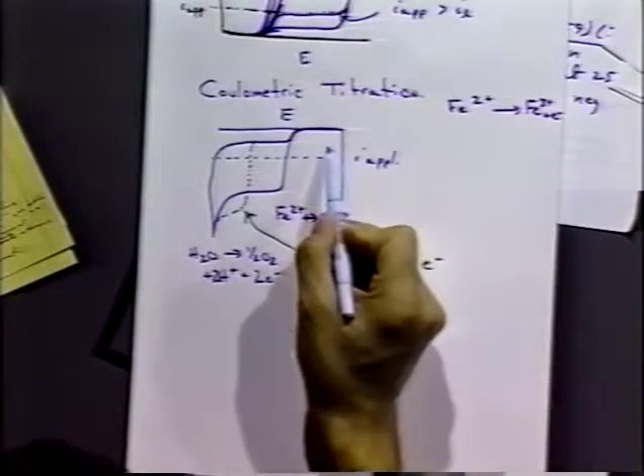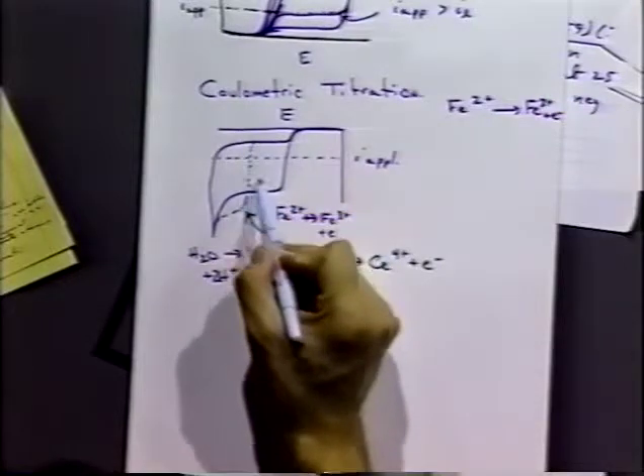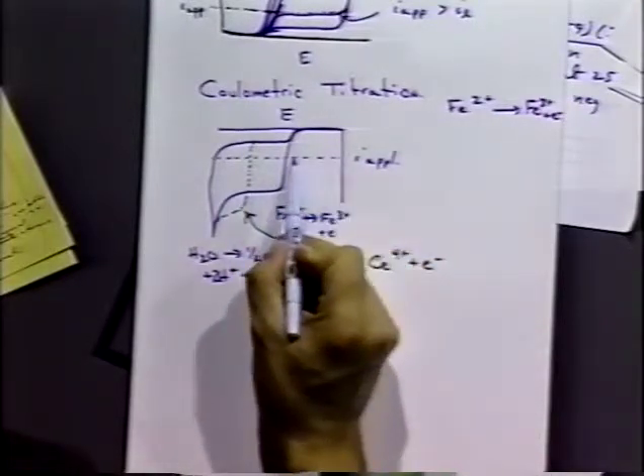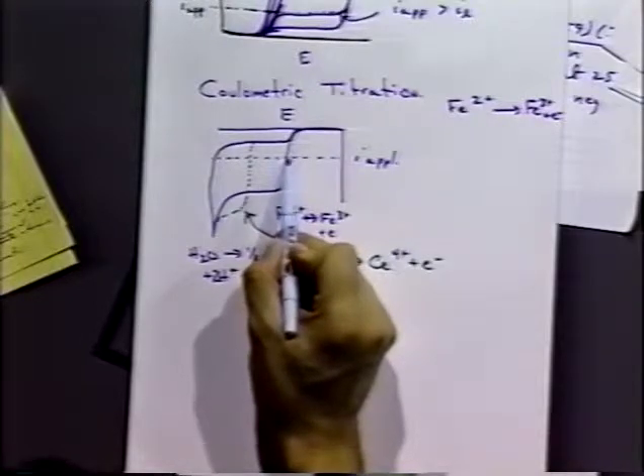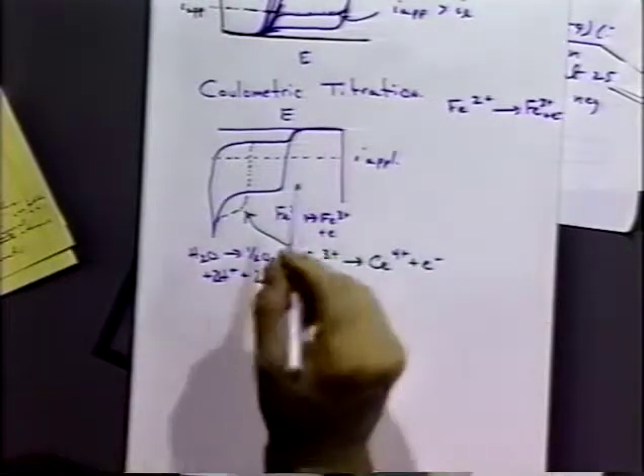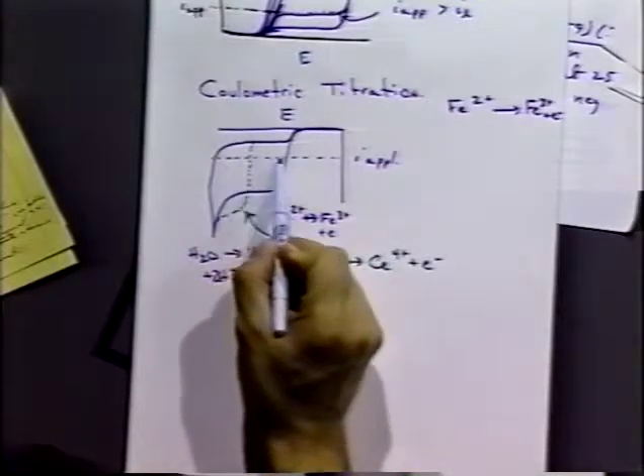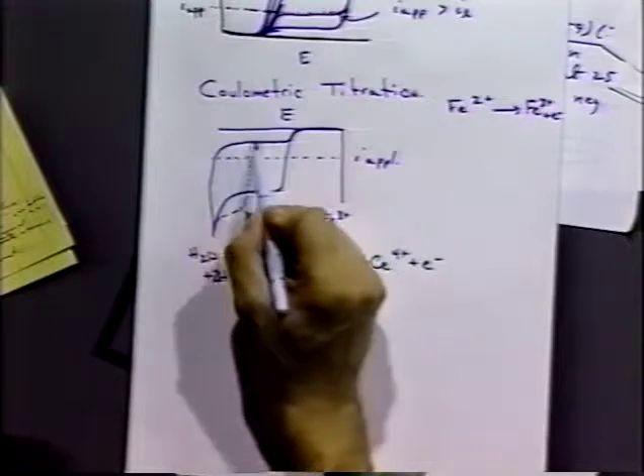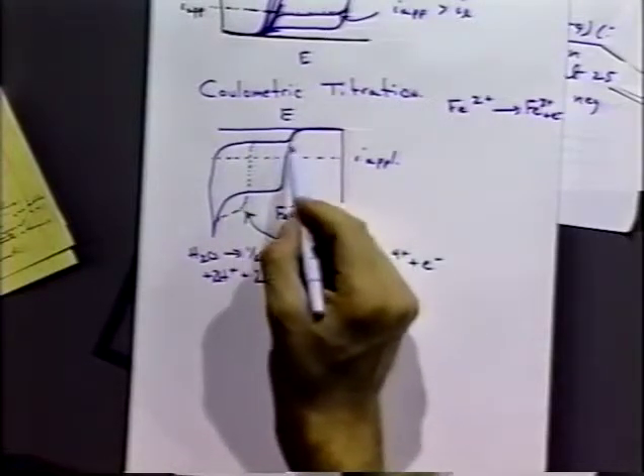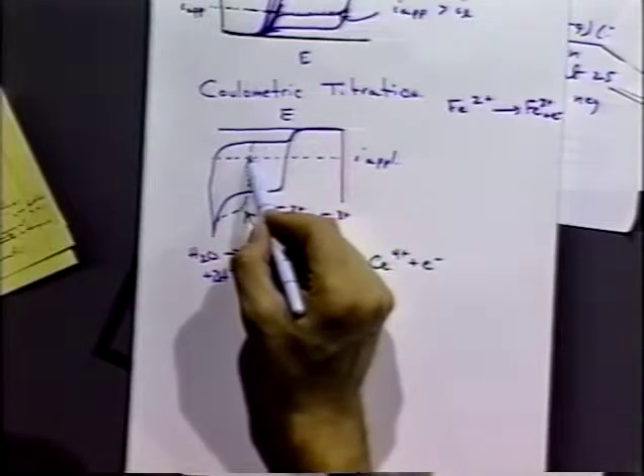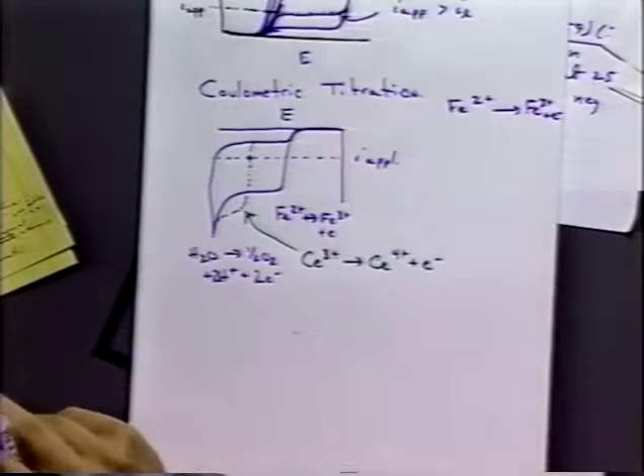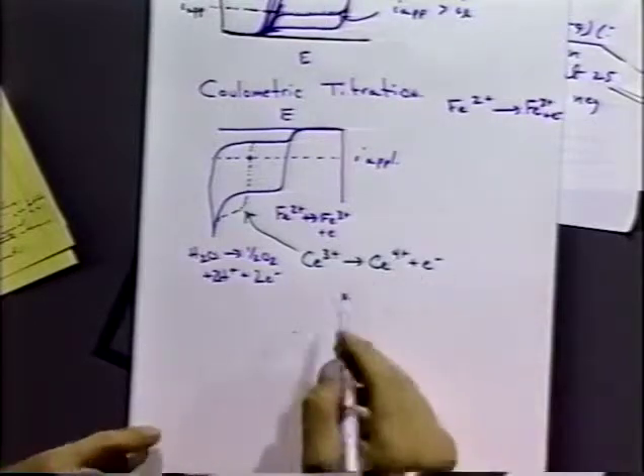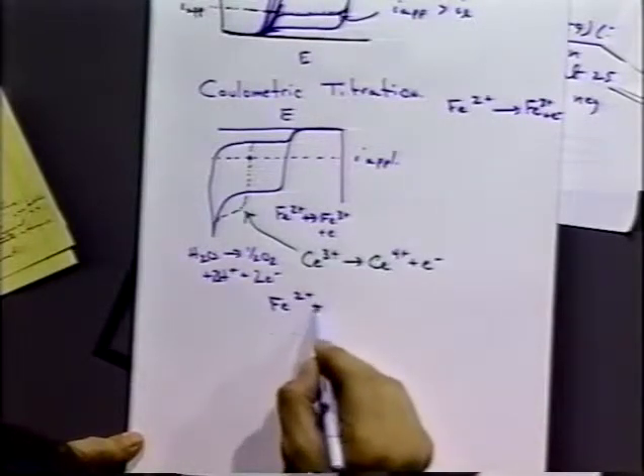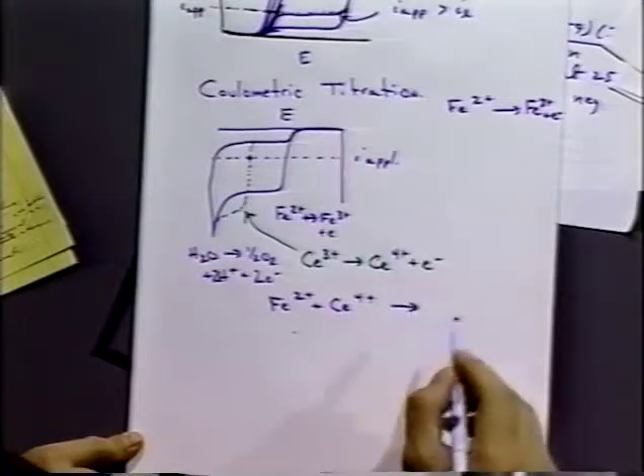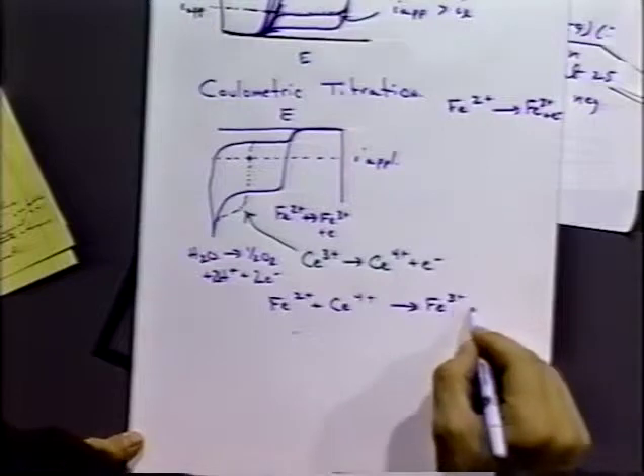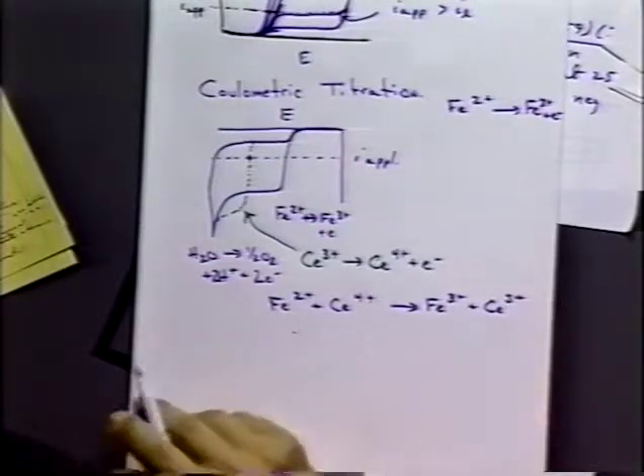But if we add an additional, excess amount of cerium 3 in the solution, initially we'll be applying current and we'll be mostly involved in oxidizing iron 2 to iron 3. However, as soon as we get to a situation like here, where the current is lower than the limiting current for iron 2, we get to a point where now we're going to start generating cerium 4 efficiently at the electrode itself. And so iron 2 plus cerium 4 goes rapidly and quantitatively to iron 3 plus cerium 3.